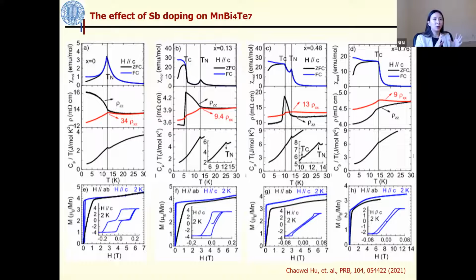So when you dope it, initially our idea was just to change this anisotropy parameter, but it turns out it was not just what we thought. This doping introduces many more antisite disorder, and this antisite disorder has an exchange interaction term. So therefore, it's not just a local manganese environment change, but also a change in the defect chemistry, and as a result it changes the exchange coupling here. Does that answer your question?